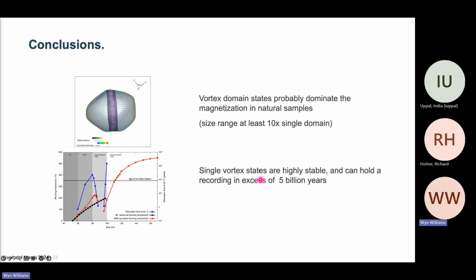Okay, to the conclusions. I'm sorry for taking so long. The main takeaways, the most important parts, is that these vortex domain states probably do dominate most of your paleomagnetic samples, and they are very stable, more stable in fact than single domain grains. This is great news for paleomagnetism, great news for planetary science as well, that we have the possibility, in principle anyway, of being able to record these events that are billions of years old.